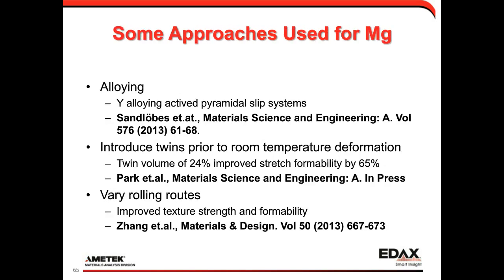This is just a slide showing some of the approaches being used to improve magnesium. Alloying with different materials will activate different slip systems. Introducing twins prior to room temperature deformation improves formability, and vary different rolling routes can improve the texture, strength, and formability. For all of these, being able to characterize the microstructure with EBSD gives an idea of what's occurring fundamentally within the microstructure to give these properties.